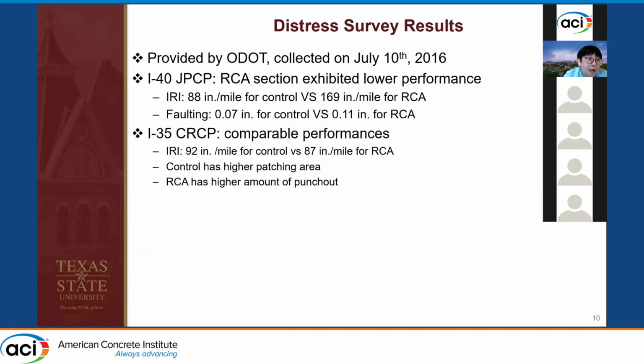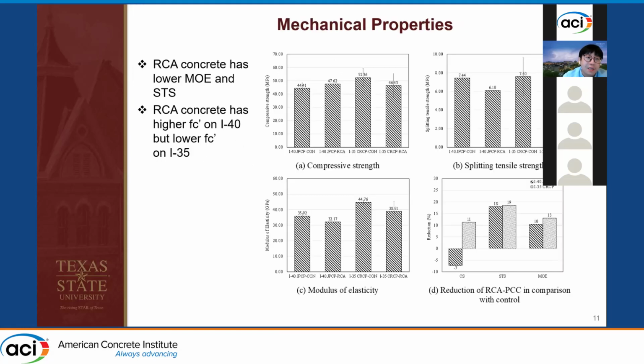For the CRCP located on I-35, the performance was very similar between RCA and the control sections. The IRI value was close. The control section had a higher patching area, but the RCA section had a higher amount of punchouts. So we consider they had a similar performance on the I-35 for the CRCP sections. We also did mechanical properties testing on our cores from the field. The major conclusions are that RCA concrete has lower modulus of elasticity and also lower split tensile strength.